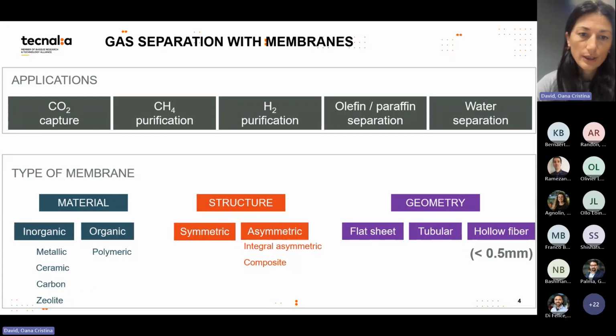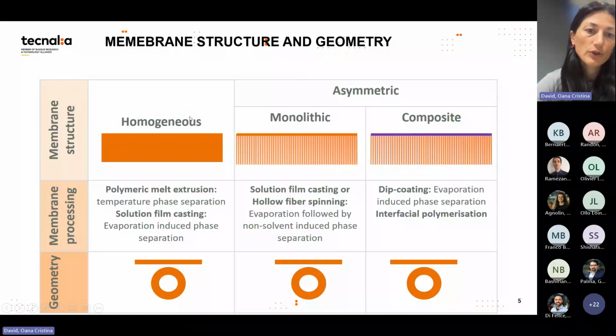As was already said today, the structure can be either symmetric or asymmetric. And the geometry can be either flat sheet or tubular, and if these tubes have an outer diameter lower than 0.5 millimeters, they are called hollow fibers. In more detail, we always make a homogeneous dense film in order to characterize the intrinsic gas permeation properties, as we already showed today. These are made either by extrusion of a polymeric melt or by evaporation of a polymeric solution which was deposited as a film on a support. And here the term phase inversion is related to the fact that the polymer goes from a fluid state into a solid state.